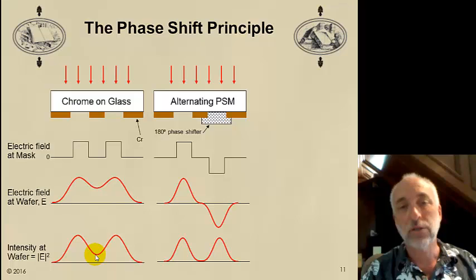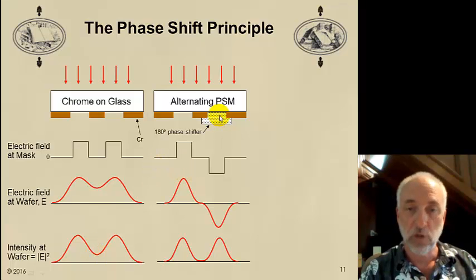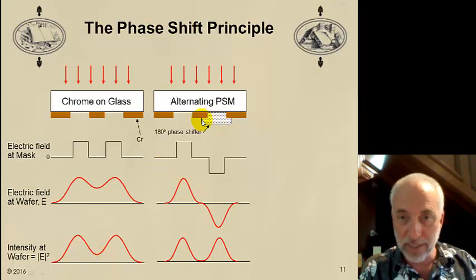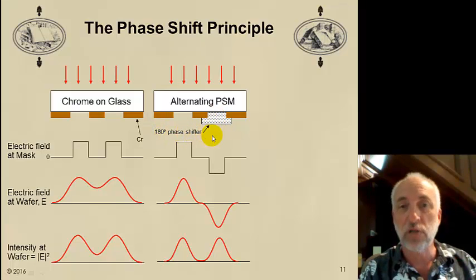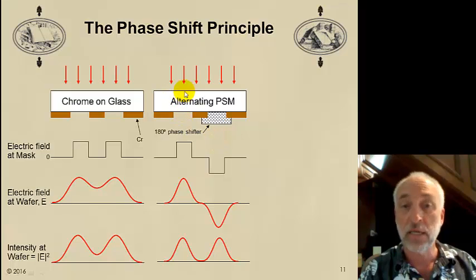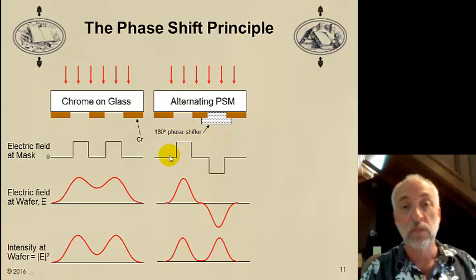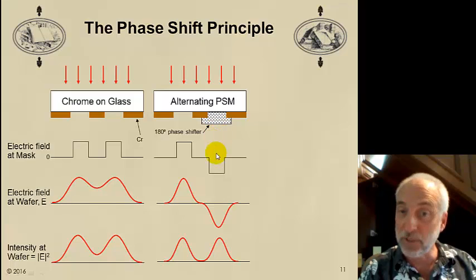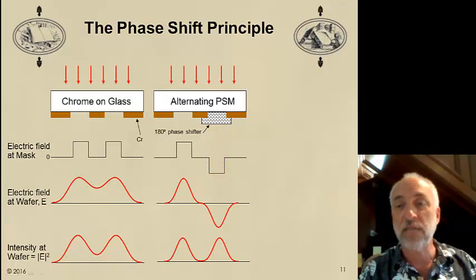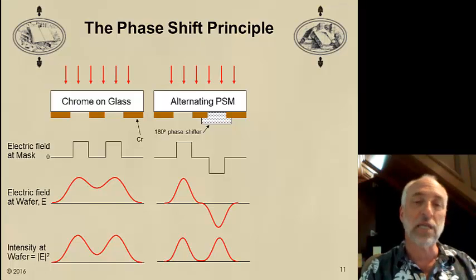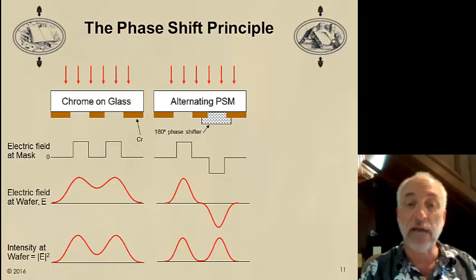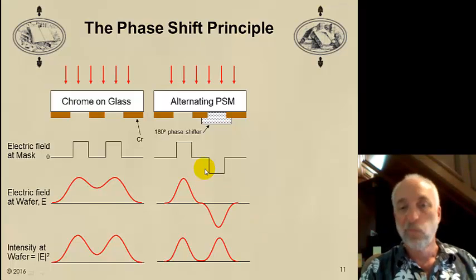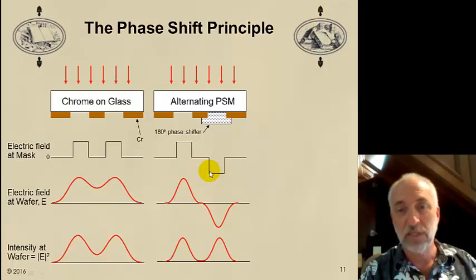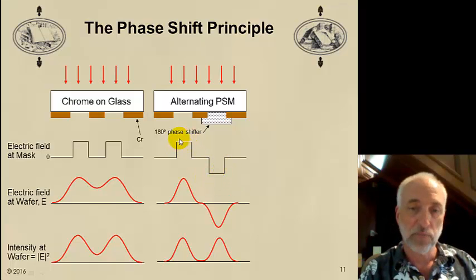What if I took some phase shifting material and added it over one of the spaces? So I put a thickness of glass underneath this right space, exactly enough to produce a 180 degree phase shift of the light compared to the space that doesn't have the glass piled on it. Well, the electric field can be drawn something like this. Still, 100% of the amplitude goes through the shifter, but it's shifted in phase by 180 degrees. We can draw that by saying the electric field has a value of -1 instead of +1. So -1 simply means that electric field is shifted by 180 degrees compared to the +1.